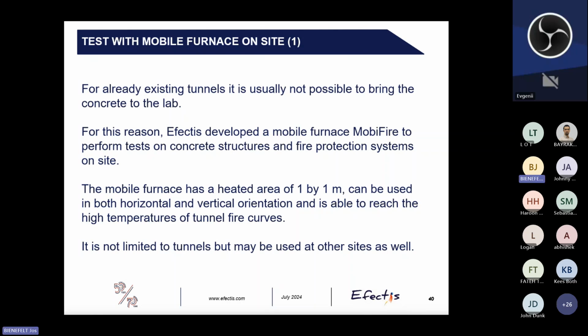So the mobile furnace has a heated area of 1 by 1 meter and is able to reach the high temperatures of all the fire curves that we've seen before. So also the RWS fire curve, which goes in 5 minutes to 1100 degrees Celsius. So the mobile furnace is not only limited to tunnels, but we can use it at other sites as well.